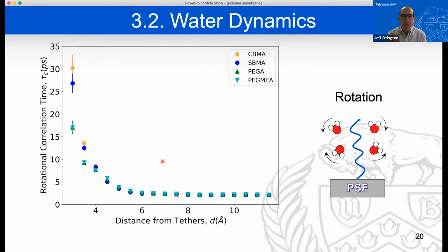The next thing that we looked at was the rotational dynamics. And so here we captured the rotational correlation time. And again, we captured this as a function of the distance that water is from one of the heavy atoms associated with the polymer chain. So again, just in aggregate, the time correlation decreases as you move away from the polymer tether. In other words, the water becomes less mobile as you approach the polymer tether.